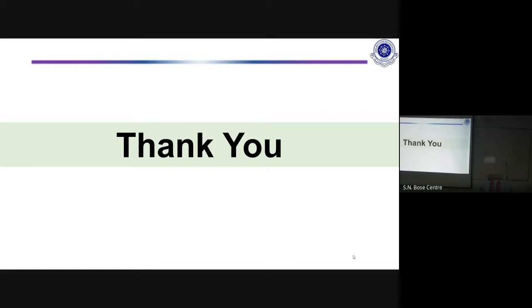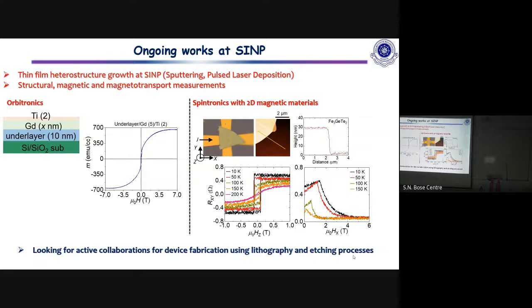How thick was your active plate? This is around 30 nanometers. This is the AFM image. It's roughly around 30, so still we have something like a bulk. Yes, but according to literature, around this thickness you should have a single domain. It should behave like a single domain magnet. So that is what was actually the original idea.